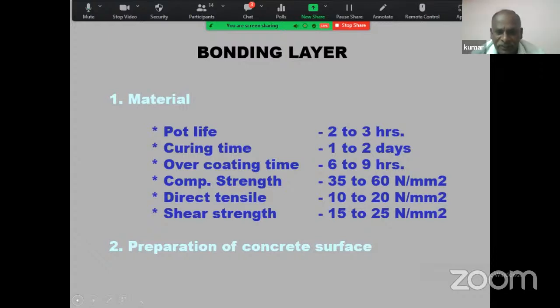For the material you can use, the pot life is 2 to 3 hours, curing time 1 to 2 days, overcoating time 6 to 9 hours. These are the compressive, direct and shear strengths. In such a way you can select a proper bonding layer and utilize it. Application may be either by brush or spray, any of the kinds, you can use for the bonding layer.